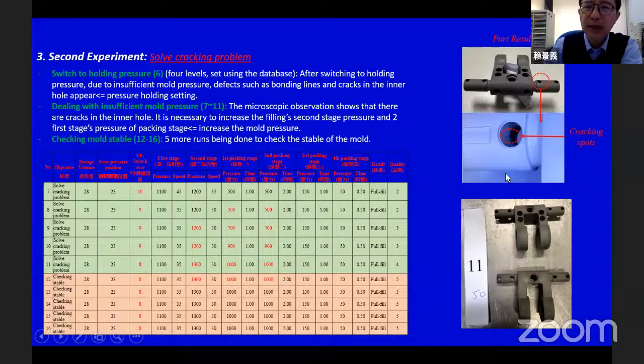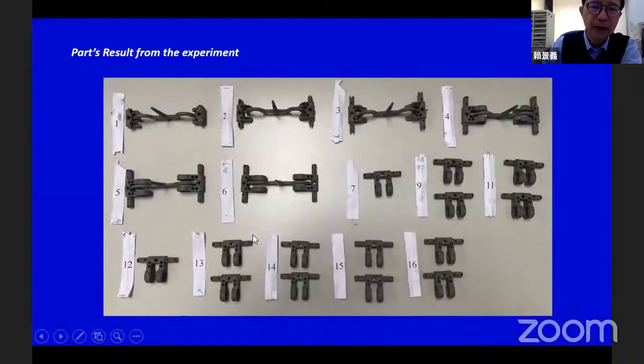And then for the entire process, we had some defects. We needed to adjust some of the parameters to try to remove some of the defects, and so this is the final result. I think from 13 to 16, those results are satisfactory. Before that, we had some defects, so we needed to adjust the parameters to overcome those shortfalls.